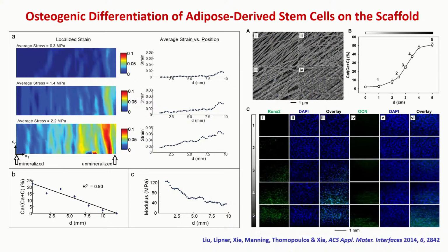And then we cultured stem cells. These stem cells were isolated from adipose tissues, and then we seeded them onto this scaffold and cultured them. We compare five different regions with the mineral coating increasing from 1 to 5. Basically this is just shown in this curve. You see the calcium content increase in this way. And after culture for 7 days, and this is 14 days, we can use 2 different types of markers to see how the cells have differentiated.